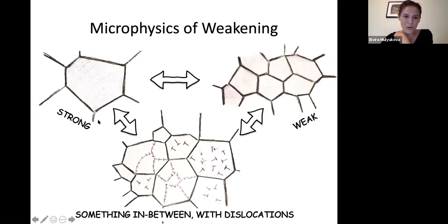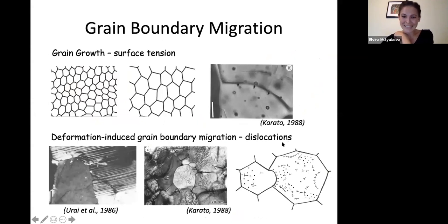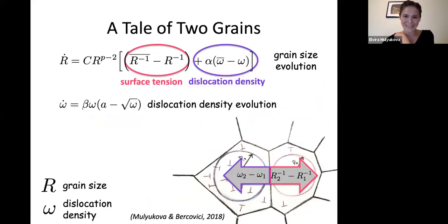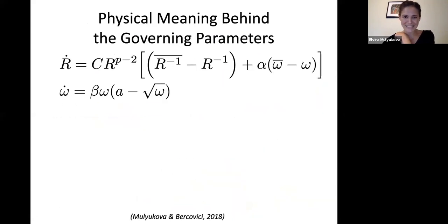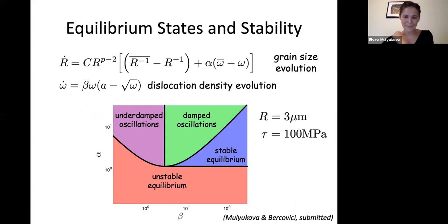Okay, so as we go from strong coarse grain material to weak fine grain material, I've shown you before that we wanted to look at interactions of dislocations and grain sizes. And so in another theoretical model, we had evolution of grain sizes and dislocation density simultaneously. I'll just go through this fast. The most important part of these equations is here. So we put together a theoretical model for evolving grain size as driven by surface tension, as in normal grain growth, and dislocation densities by processes I explained earlier. And we have evolution of dislocation density. This is just a simplified version of the equation I showed you before.